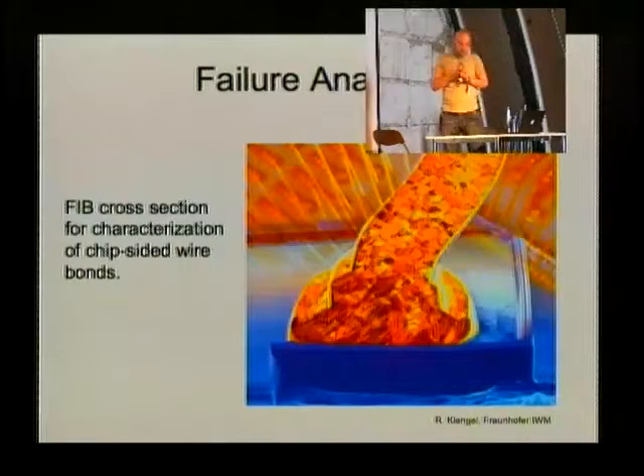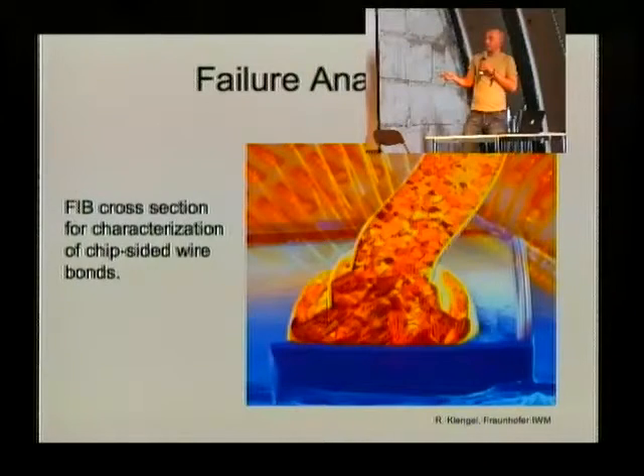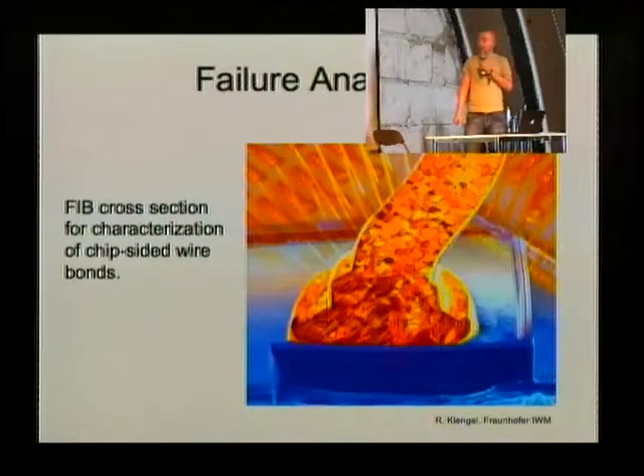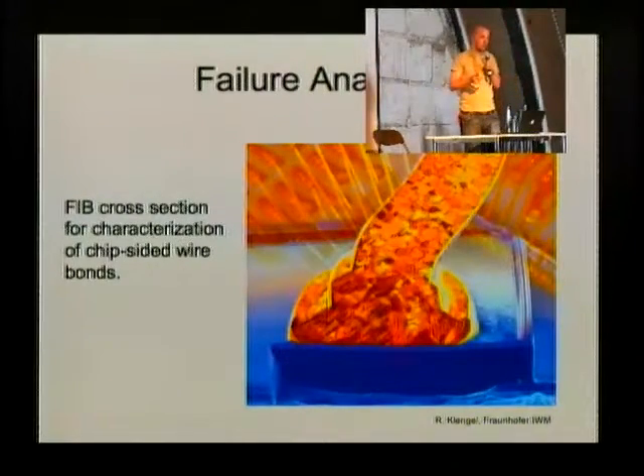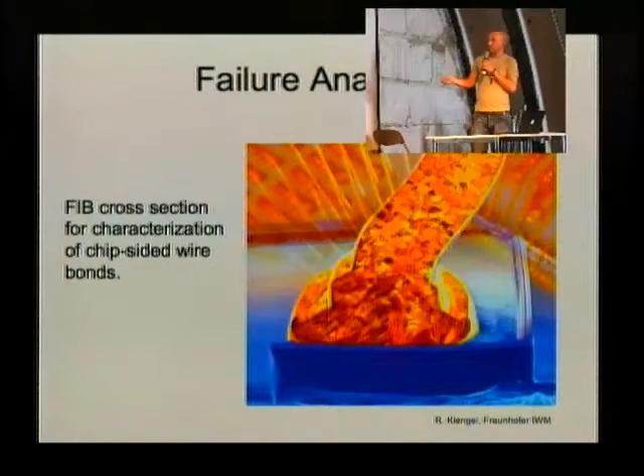So, why is it so nice for failure analysis? What we see here is the chip-sided bond of a gold wire, and there are many factors governing how this wire bonds, and this is a common cause of device failure, that one of these wires breaks or gets detached from the substrate. So the FIB allows you to basically cut this soft wire and cut through the very hard silicon without changing the surface. You can nicely see here you get a very clean cut, exactly where you want it to be.